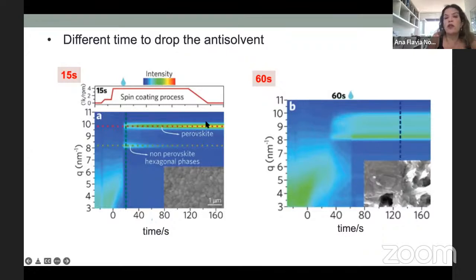Okay. Of course, we changed many parameters in this work here. But I want to show you here that this time to drop the antisolvent is really crucial. You need to drop the antisolvent while you still have the signal from the precursor solution. Okay, see this blurry signal here. So you need to have this signal from the precursor solution. If you drop where you don't have this signal anymore, the morphology is really, really poor.